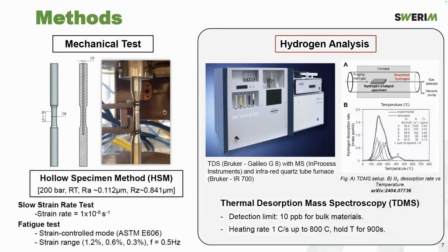For hydrogen analysis, we use TDS with mass spectroscopy and an infrared quartz tube furnace. And well, everyone here knows how it's used. The heating rate used for this project is 1 degree per second up to 800 degrees, then we hold that temperature for 900 seconds.